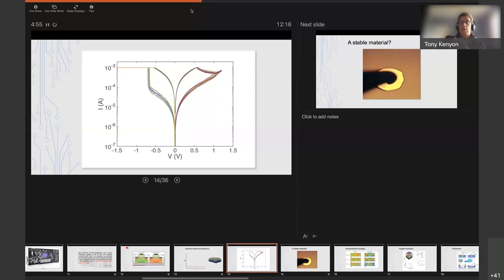But if we apply a bias to it, it's also quite good at then putting the oxygen back into the silicon. And the reason for that is if you look at the thermodynamics of the oxidation of silicon and the oxidation of titanium, then one of the quantities that governs whether something will oxidize is Gibbs free energy. And the lower the Gibbs free energy, the more likely you will see a particular reaction, in this case oxidation. Well, it turns out the Gibbs free energy of oxidation of titanium and of silicon is very similar. So that means it's relatively easy to move oxygen backwards and forwards between the two elements. If it was very different, then you'd have a big asymmetry where the oxygen would tend to go in one direction and be very difficult to pull it back the other way. So you would want a system a little bit like that. Yes, sir.